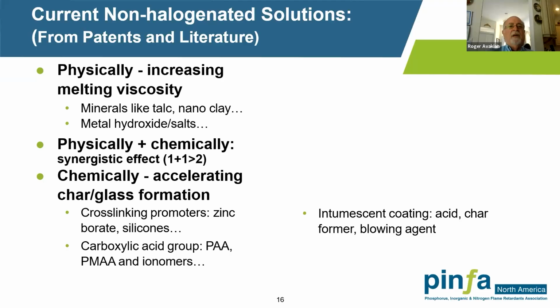One is physically, by increasing the melt viscosity, such that the material does not have this tendency to drip. This can be done with minerals, for instance, like talc, nanoclays, and some other types of minerals we'll talk about. Also metal hydroxides like magnesium hydroxide and aluminum trihydrate, in sufficient levels, will do that. There's also a physical and chemical, sort of synergistic effect. Can you get this increase in melt viscosity while also charring the material? And for instance, branching the material such that you do get this increase in viscosity.